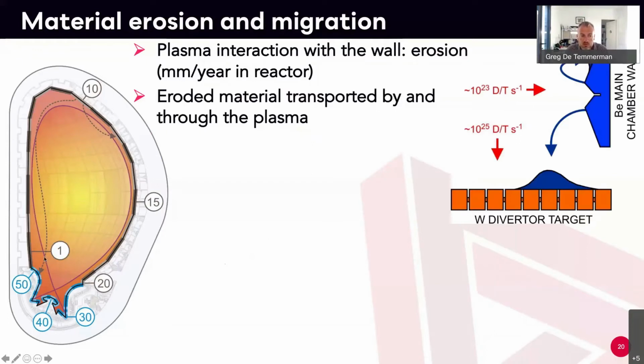I won't go too much into the details, but typically what happens if you look at the cross section of ITER is that the particles will bombard everywhere. They remove particles here. Those particles get ionized. They get transported by and through the plasma, so they circulate inside the machine, and then they end up being deposited somewhere else. So typically you would have an area on which you are removing atoms all the time, and then those atoms are going somewhere else, either in the divertor or close to where they originated from. If you look at a reactor, you could have millimeters per year of erosion. So you have to make sure that you have enough thickness for your material to actually live long enough.